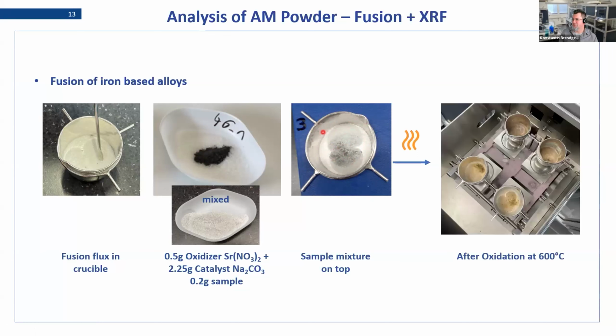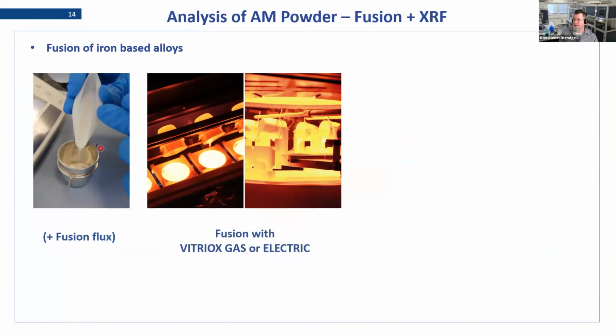So we oxidize this. This can be done in a muffle furnace. In this case, we used our fusion machine for this. The oxidization is, I think, 12 minutes. Once this is finished, we let it cool down, and then we add the rest of the flux on top. And then we do the actual fusion. Also in this case, on the left, we have our electrical one, but you could potentially also do this with a gas fusion machine.